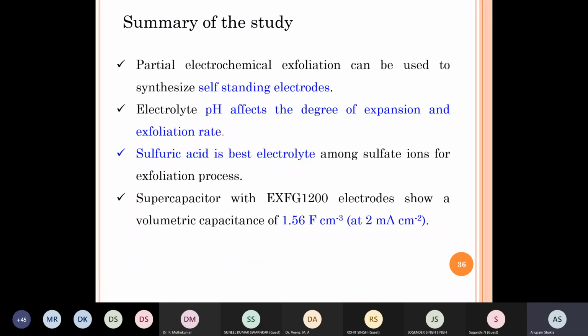Okay, so just to summarize, it was shown that partial exfoliation can provide self-standing EDLC electrodes. Electrolyte pH affects the degree of expansion and exfoliation rate, and therefore played an important role in the density of graphene nanofilms that one can get.